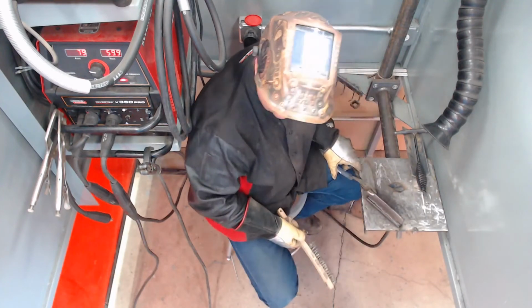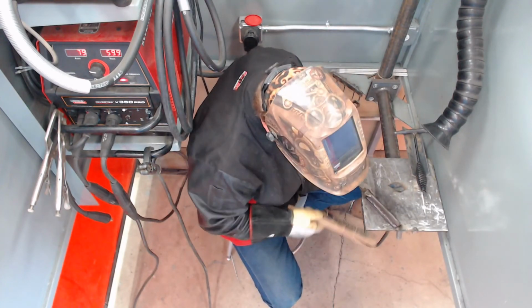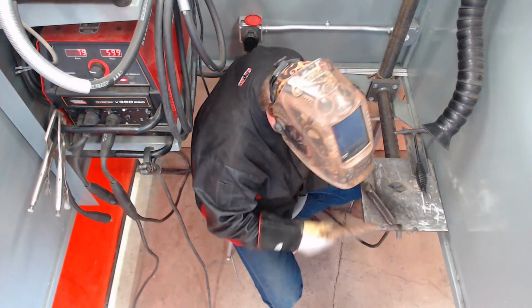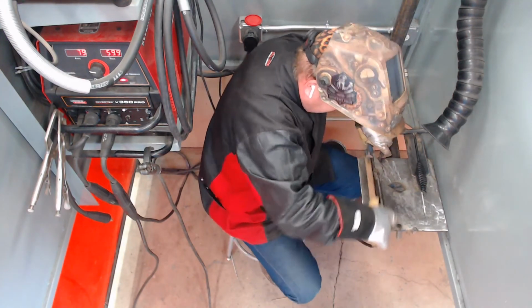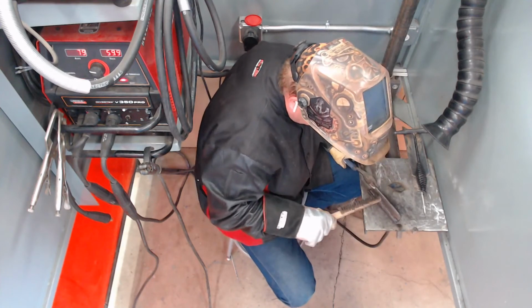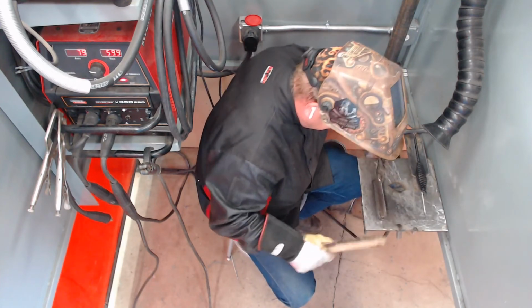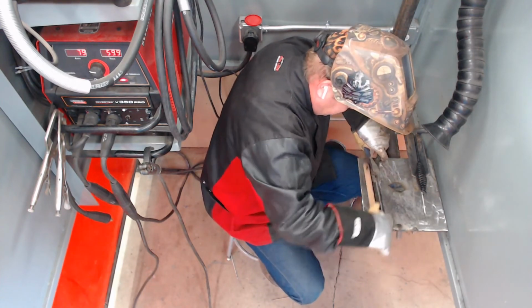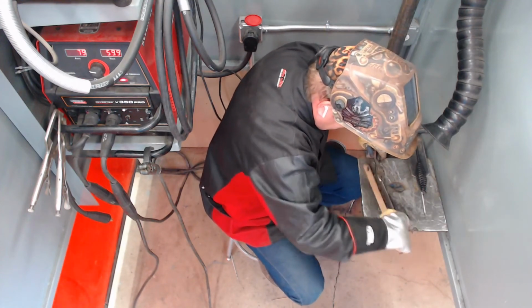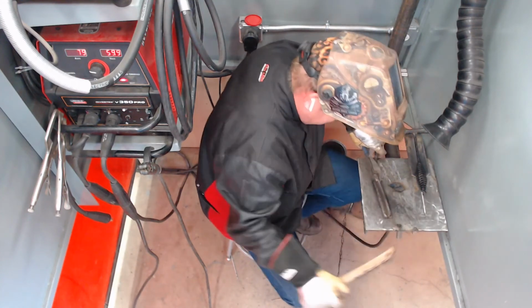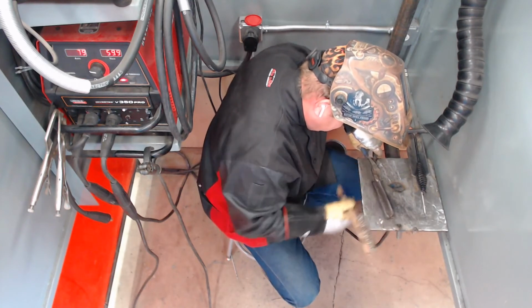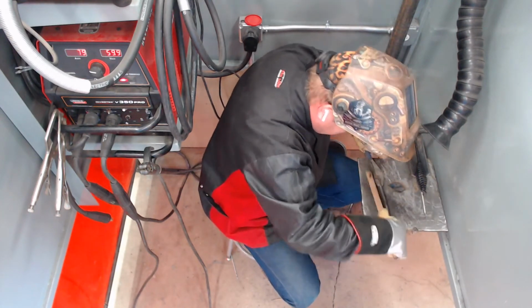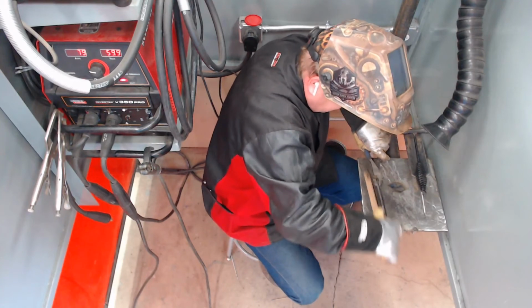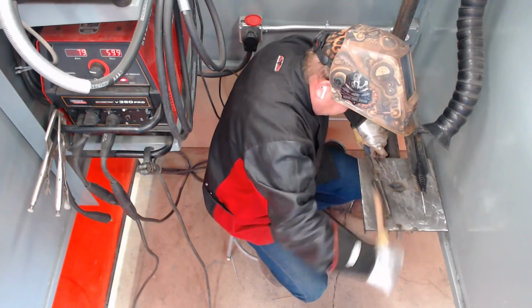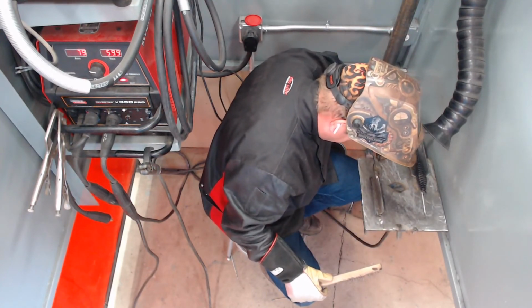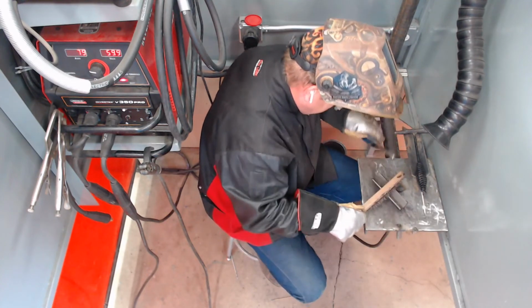Okay, if you look real close, you can see what cranking down the amperage a little bit has done to my weld. It's cleaned it up quite a bit. Still getting good penetration. The weld's looking nice and flat like it's supposed to. Now if I was on a job site and I was worried about this weld passing inspection, I would have this thing out on a wire wheel and clean this slag out real good. But I'm getting the majority of it with my wire brush. It's looking pretty good.